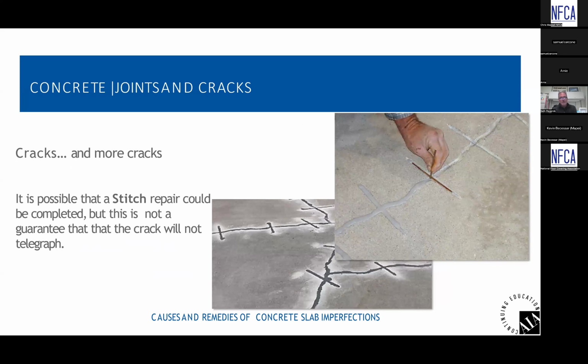One possibility of repairing cracks would be a stitch application, as you see in the picture here, basically making perpendicular saw cuts across the crack and dropping in, I've seen guys do masonry nails or small rebar, and you use a two-component rigid material such as a two-component epoxy or urethane, and you're basically bonding the crack back together. The large masonry nail or rebar with the epoxy or urethane is creating a stitch to help repair that concrete. But again, while this is a remedy, as installers, it's really not your job to make the remedy. Raise the red flag, get the GC and the structural engineer involved, and this is a possibility of a repair method. Now, nothing's ever 100% guaranteed, but nonetheless, it's a possibility.